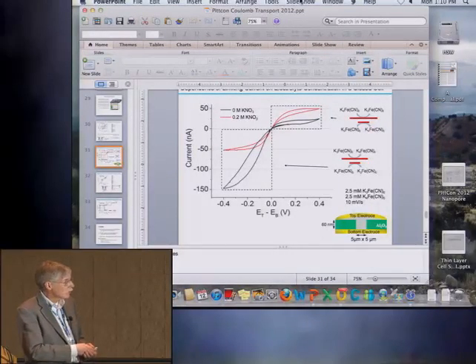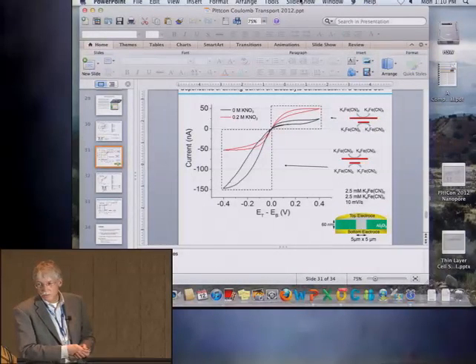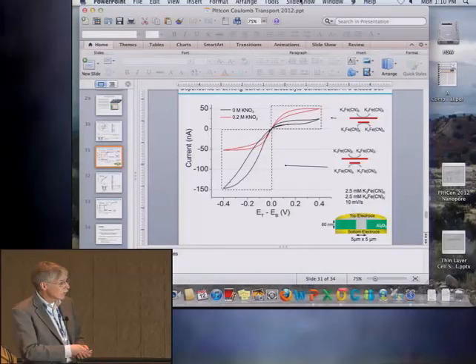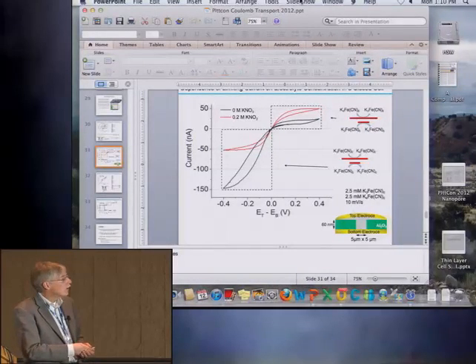The curves aren't as pretty as we'd like. There's hysteresis here that I think is probably associated with some leakage along the top electrode. The whole wave shape is not symmetrical around zero. It's centered at zero, that's good, but the shapes of the waves are not symmetrical. So there's something going on here that we don't really understand. There is clearly a big field enhancement here. You take the electrolyte out, you see this massive migrational transport, the effect on the voltammetric shape. I've drawn the top electrode a little buckled. We don't really know that, but I've drawn it just to throw that out as a possible explanation.